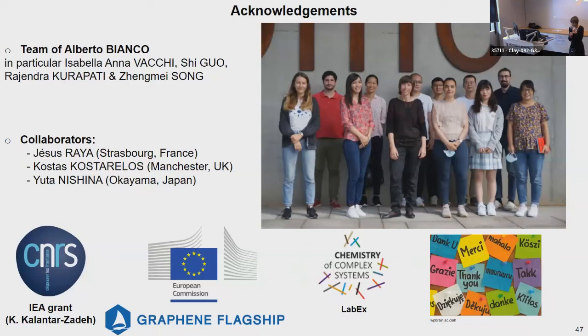We have also shown in collaboration with the group of Costarelos that the thickness of the material is also critical. By definition, graphene oxide is monolayer, but some commercially available samples may be few-layer graphene oxide. Monolayer graphene oxide can be easily eliminated from the body, while thicker graphene oxide can accumulate in some organs, and this may be critical. So yes, the size and the thickness are really crucial parameters. I would say the level of oxygen is also very important.